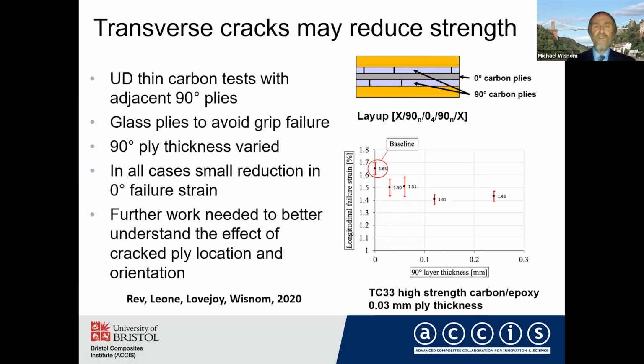I showed with the quasi-isotropic laminates that we could reconcile the 0 degree strength with the quasi-isotropic strength. But in this case, we're showing that actually the cross-ply strength, the carbon fibers are a little bit weaker than they are in the unidirectional. And this may be to do with the fact that in this case, the 90 degree plies are directly adjacent to the zeros, whereas in the previous one I showed there was 45 plies next to the zeros. So even if there were cracks in the 90s, they may not have affected the zeros to the same degree. But I think this needs some further work to better understand.